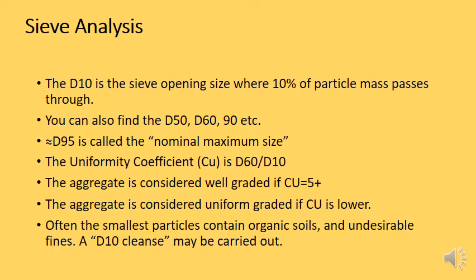Now, the uniformity coefficient is a ratio between the D60 and the D10. So let's say the D60 is actually about 5 millimeters. And the D10 will be much smaller, of course, because only 10% of the aggregate is smaller than the D10. Let's say that will be 0.5 millimeters. What would the uniformity coefficient be in this case? Well, it would be 10. It would be 5 divided by half.